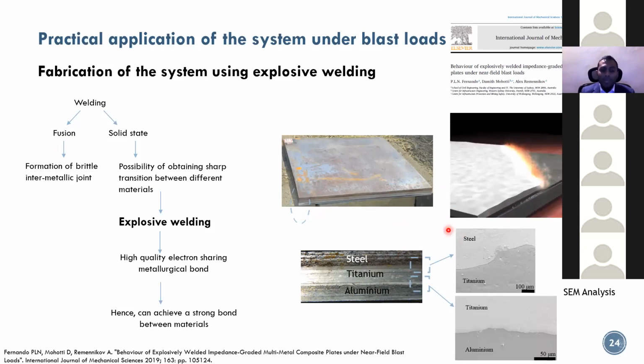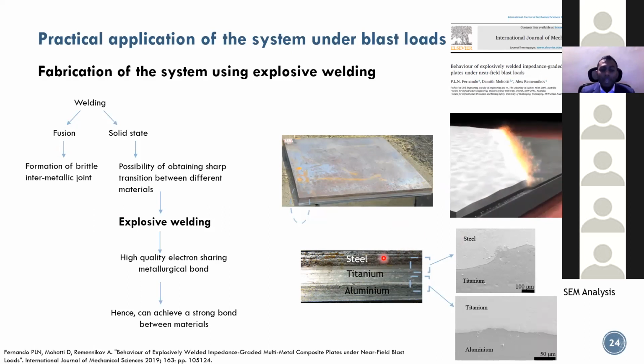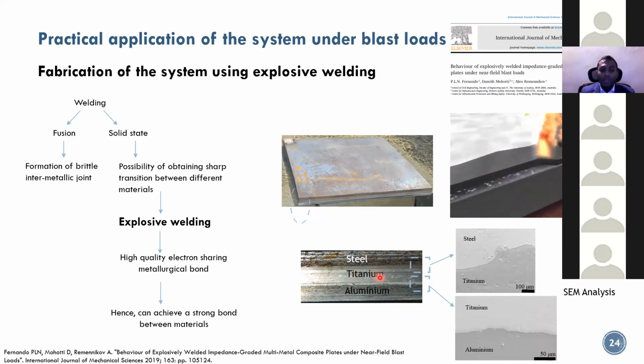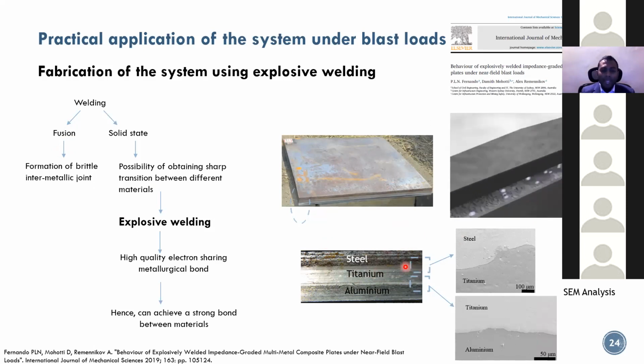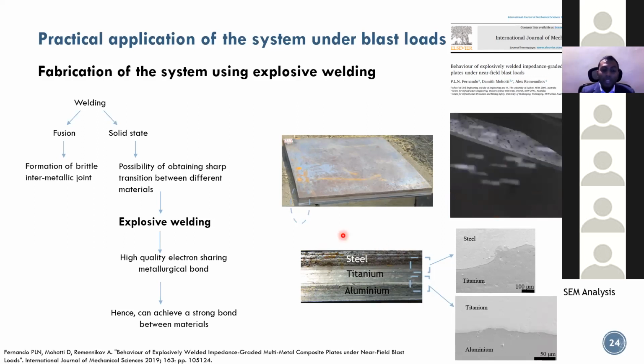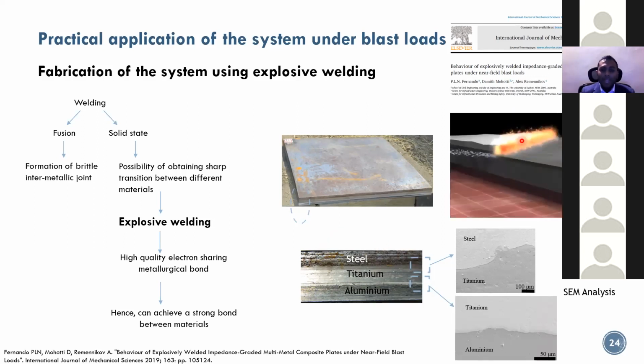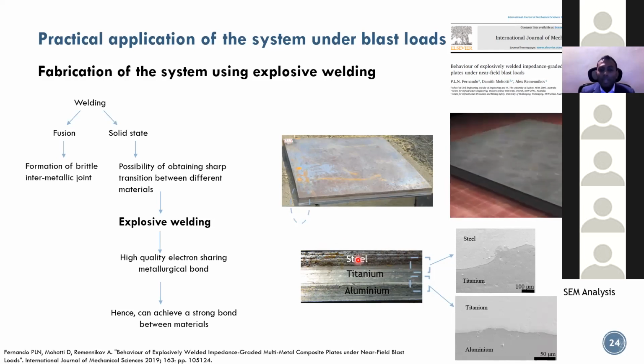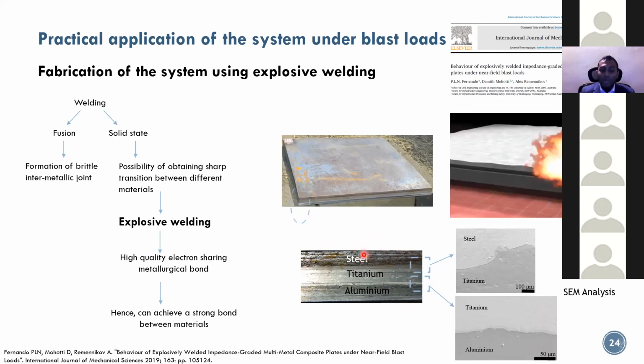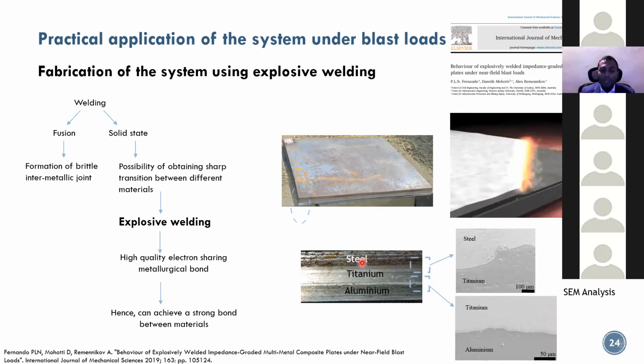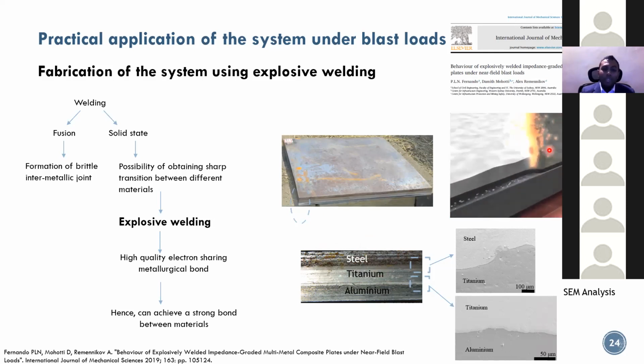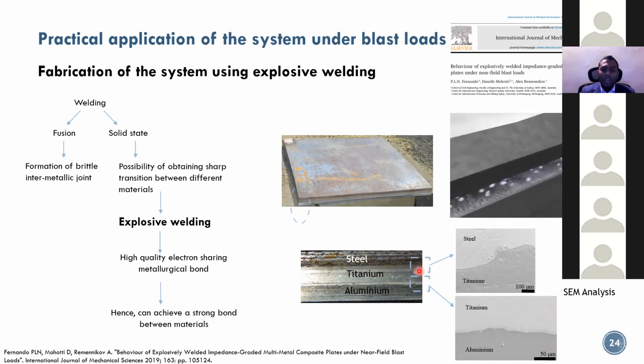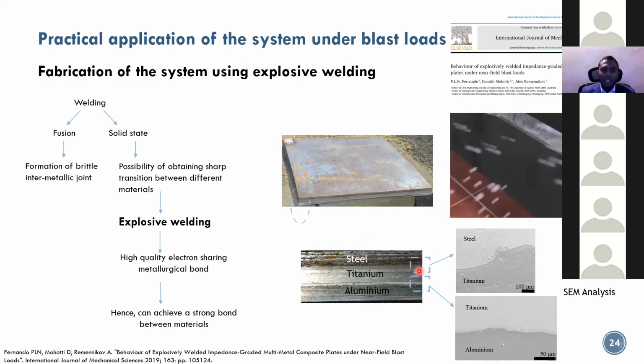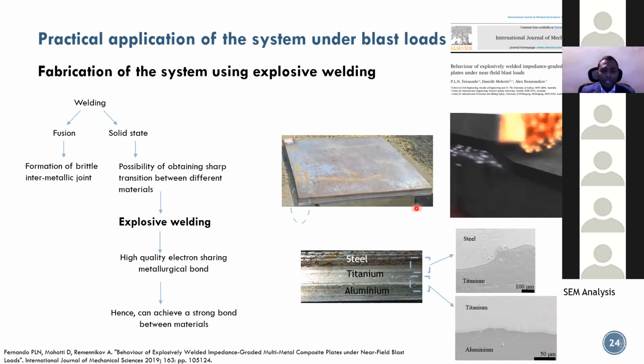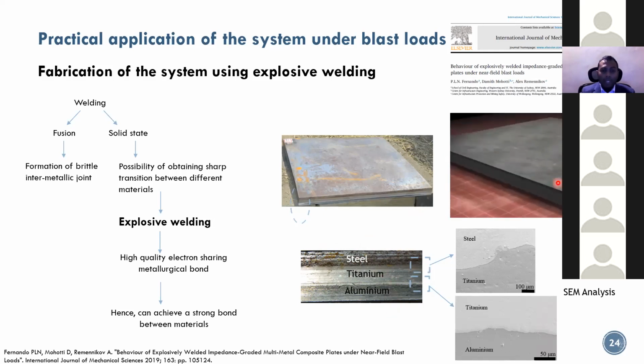So what happens is, say if you want to connect the steel to the titanium plate, you place the titanium plate at the bottom, you place the steel at the top at an angle, a slight inclination, and then you cause an explosion at the top of the steel plate. And as you can see in the video that's getting played here, without melting, because of the explosion, the steel will go and hit onto the titanium, right? And in that impact zone, as you can see from one corner to the other, just like a jet that gets formed and moves away from the source of the explosion, causing the surfaces to peel and to bond well. So this was the new material system that we came up with using this technique.